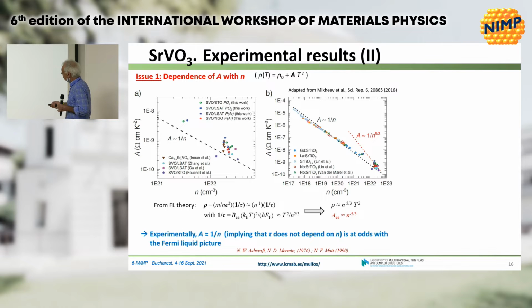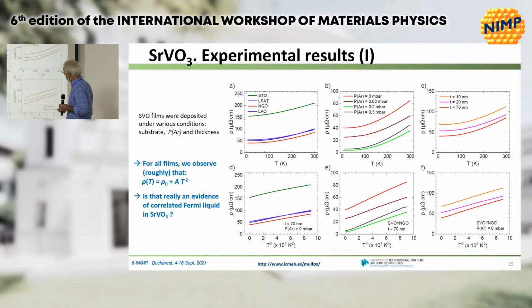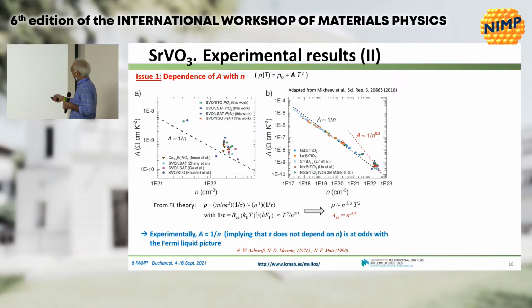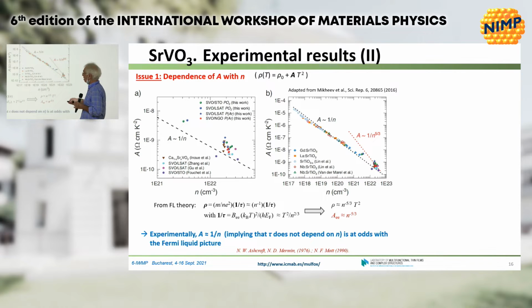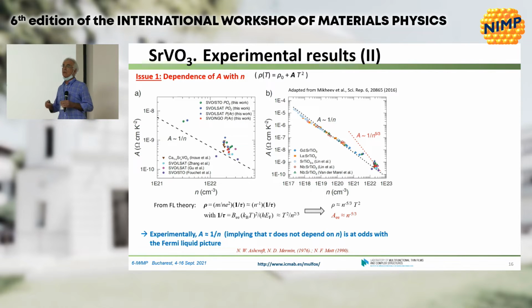Here is the plot of the slope of this almost straight line as a function of n, the number of carriers measured by Hall effect. And you see that the slope changes by orders of magnitude, varying n. This is also seen in this plot where we have collected data taken from other oxides and related materials, not vanadates, other doped insulators in which you have few electrons in the conduction band, for instance, doped strontium titanate. In all cases, you see that the amplitude of the T squared term varies enormously with the number of carriers. Not only that, the slope is almost 1 over n.